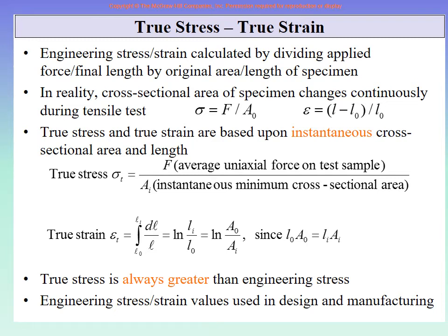Similarly, because the crosshead is moving or the extensometer is there, the change in length is not an issue. So the force value is very current, and the change in length value is very current. But the diameter is changing in the lateral direction, not in the length direction. So unless the machine is equipped with an infrared or a laser type of beam and a calculating system, which is very tough, you cannot find the current area and so on, right? So that is the issue.